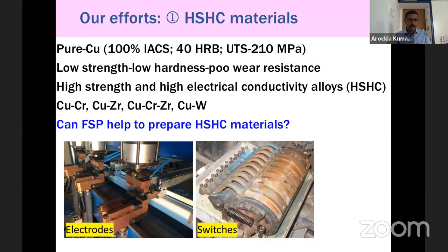So what is the remedy now? I need to improve the strength of copper. The first method is you alloy copper: alloy with chromium, or zirconium, or tin, or manganese, or magnesium, or tungsten. You can produce alloys of copper, but the problem is, once you add chromium or zirconium or any other element into copper, they try to scatter the electron movement. Thereby they reduce the electrical conductivity, which I don't want. That can reduce the electrical conductivity even down to 40% IACS.